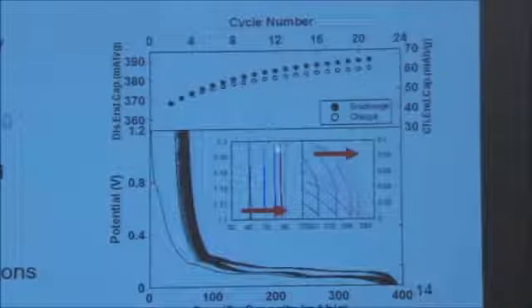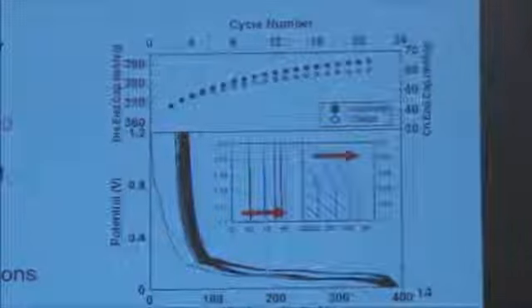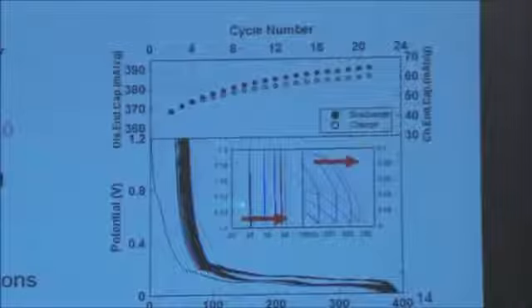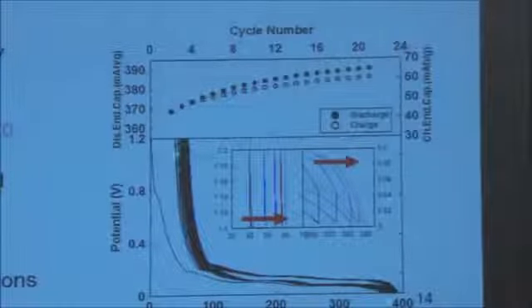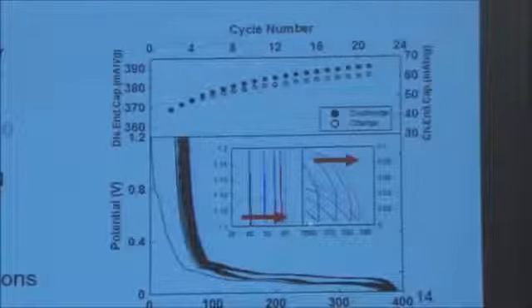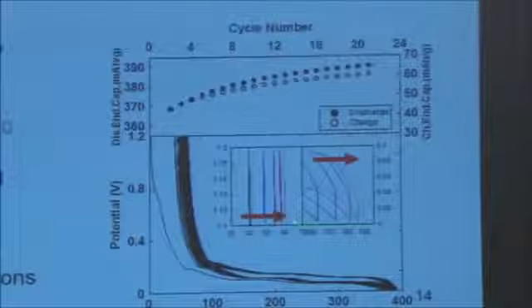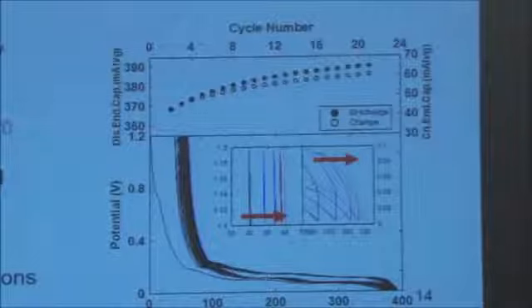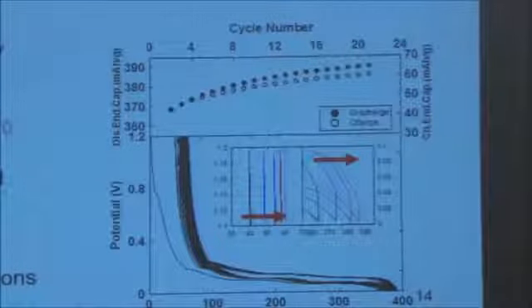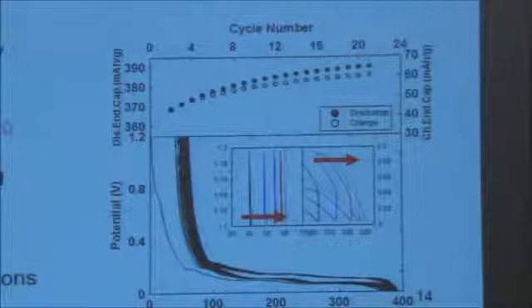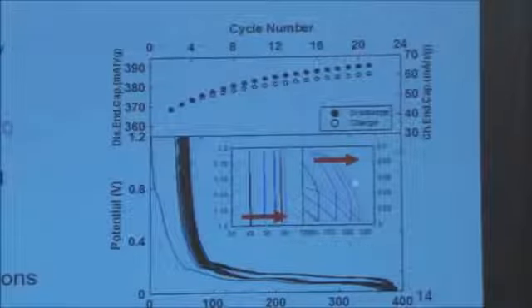In this inset panel, I show you what's happening at cycles 1, 5, 10, 15, and 20 at the top of charge and the bottom of discharge. They keep moving to the right. And the rate of motion slows down as the film gets thicker and more protective.